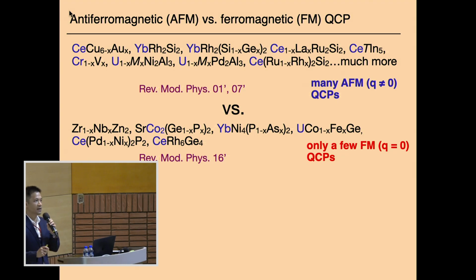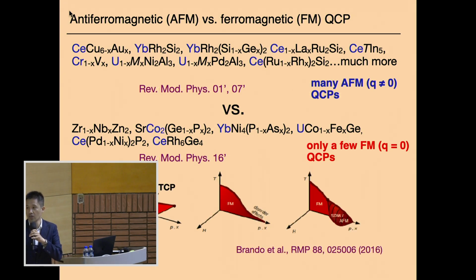Quickly speaking, there are non-critical modes that always exist, but they only couple to Q equals 0. Q is a wave number which describes how the moment modulates. For AFM, Q is not 0. So the order parameter fluctuations of AFM will not couple to this non-critical energy. But a ferromagnet will couple, and that coupling will result in the failure of formation of an FM QCP. When people try to tune a ferromagnet, that's often the result. Either, so this is temperature and this is the tuning axis, the second order phase transition will terminate at a tricritical point, TCP, and the transition becomes first order. If it's first order, it's not a QCP.